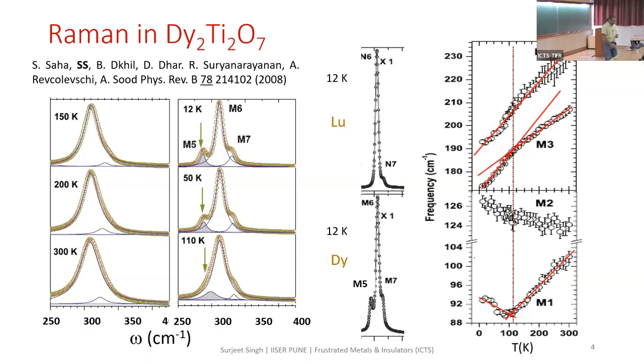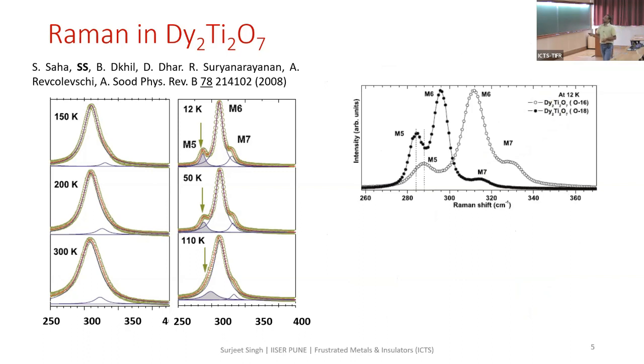So in order to see if it is indeed a crystal field excitation or related to a structural change, we did a very nice experiment where we enriched our crystal specimen with O18. With O18, we have a heavier ion which is vibrating, but nothing has changed as far as the electronic charge cloud is concerned. Now the crystal field splitting depends on the electric field of the oxygen ions. Since you have not perturbed the charge cloud, if it is really a crystal field excitation, it should not change with this isotopic substitution. On the other hand, if it is a phonon mode, then of course it will get displaced. So this is exactly what we see.